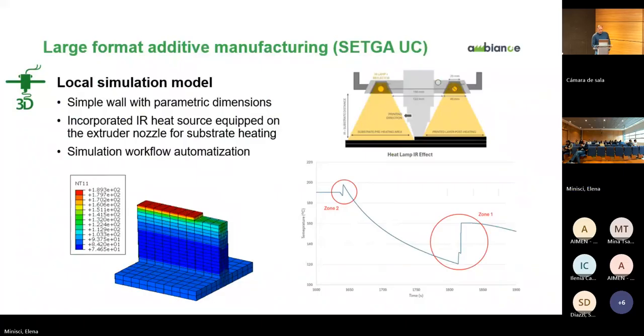We can see here that the material, once it has been deposited, suffers a small heating. That is when the posterior part of the lamp is heating what has been deposited. And then when we have reached the substrate temperature, the infrared, before printing the new layer, is heating again, and we have this jump in temperature. That is the effect we are looking for: the temperature of the substrate before the new material comes. So more or less these two jumps are quite similar in magnitude, and this is the point we are interested in extracting from the simulation.